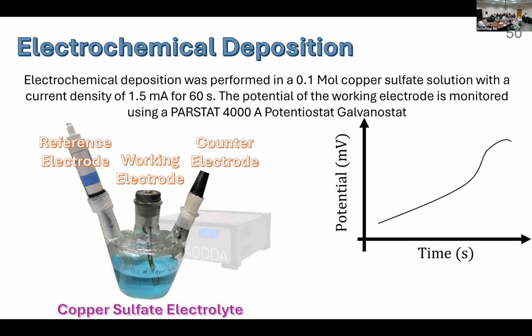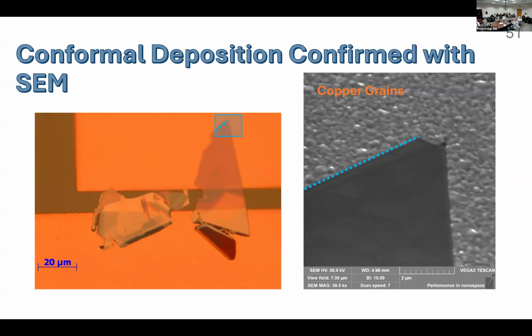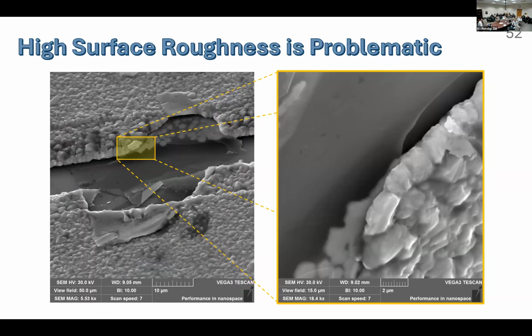After the deposition takes place, we go ahead and take optical and SEM images, and we confirm the conformal deposition of copper along the sides of our MoS2 flakes. So you can see here, this is the MoS2 flake, and this is the copper deposited on the sides of it. However, from the SEM image, you can see that there's high surface roughness, which is problematic. Imagine going down Little Italy really fast. It's not going to be fun. That's exactly what these electrons are going through when they're traveling through this.